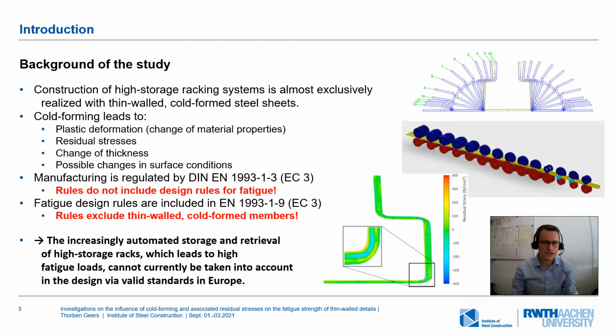The cold forming leads normally to a plastic deformation, which results in a change of material properties in the bending areas, and it definitely leads to residual stresses. Additionally, it can lead to changes of the thickness of the sheets in the bending areas, and it can lead to possible changes in surface conditions. This manufacturing process is regulated by the Eurocode 3 Part 1.3.